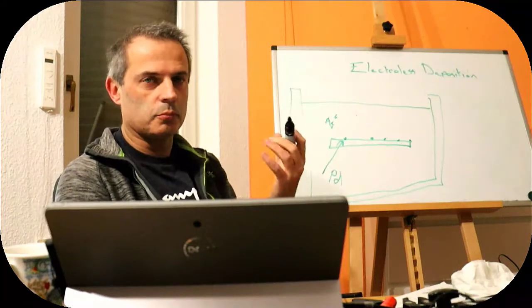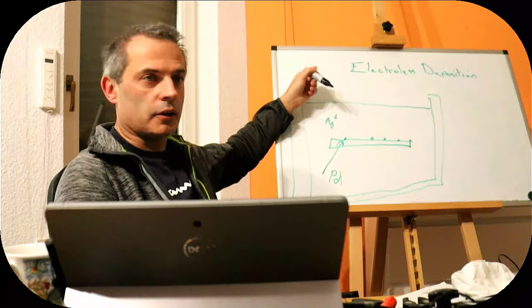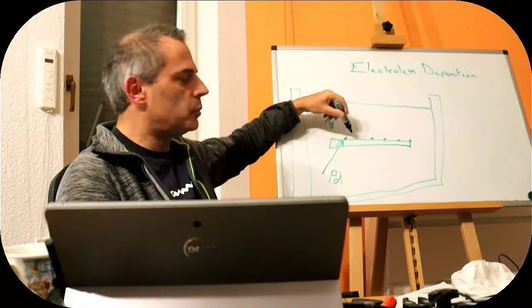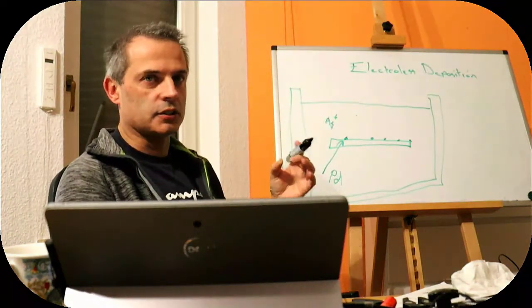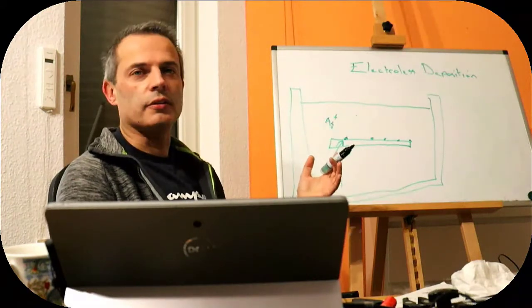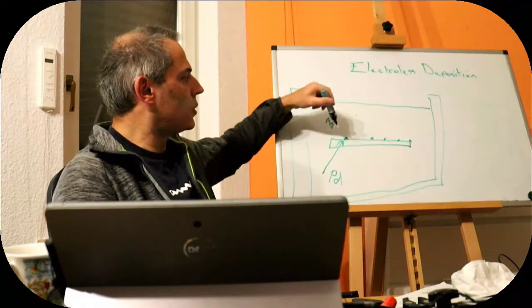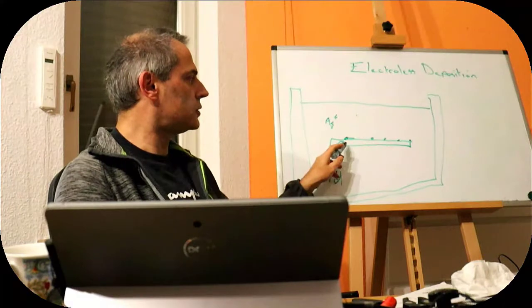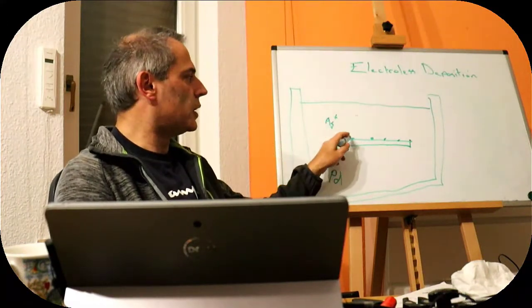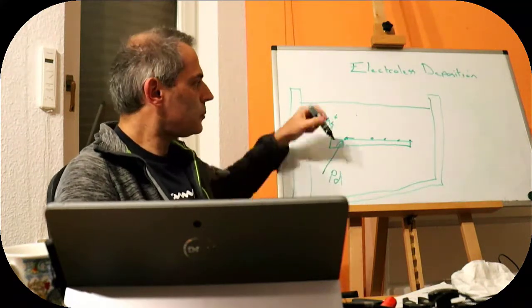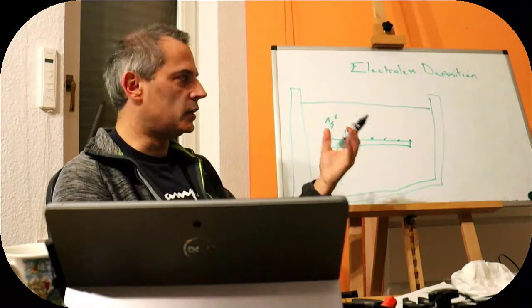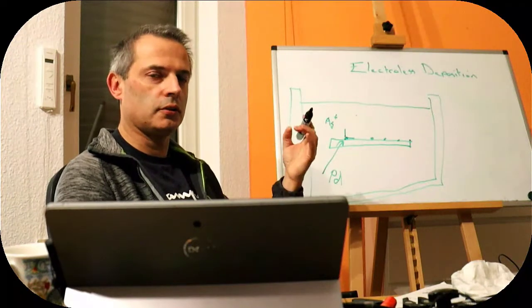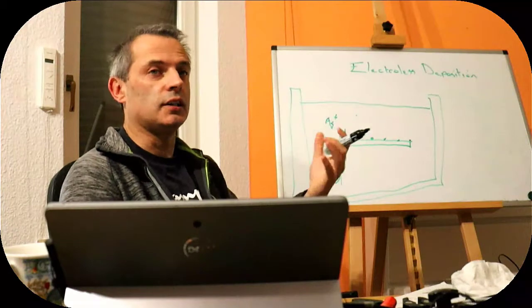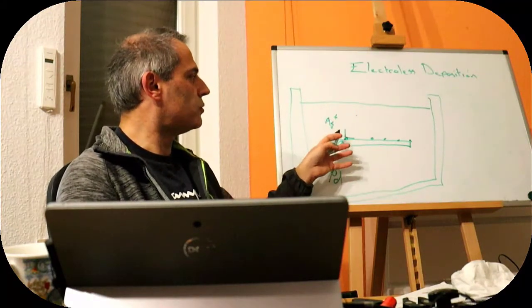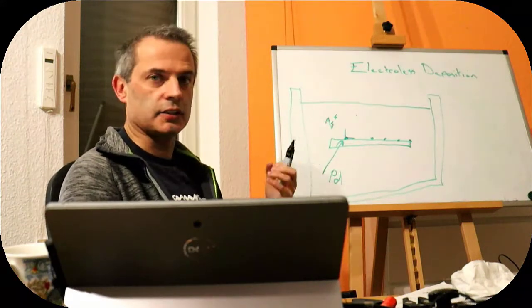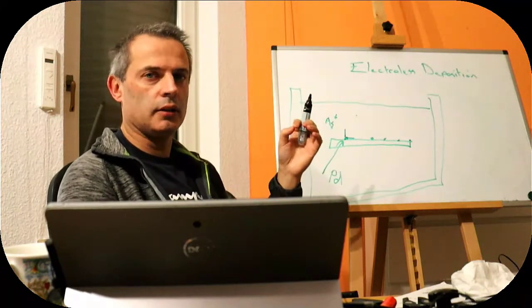The more important thing for our particular topic is what is going to happen here, because out of interest, the silver is going to start to deposit on our palladium particle, and it will increase in size. One of the driving forces is minimizing surface energy. One of the ways it can minimize surface energy is to grow along the surface, as long as our glass, in this case, is high enough surface energy that our silver can stick to it and it doesn't cost too much extra. Growing out into solution will generate new interfacial area, and that obviously comes with a cost of surface energy. Typically, making metal surface area is costly in surface energy. Metals have a very high surface energy, and therefore it is less likely to do that unless we have excess energy in our bath, and we don't have that because we've deliberately just nudged it.